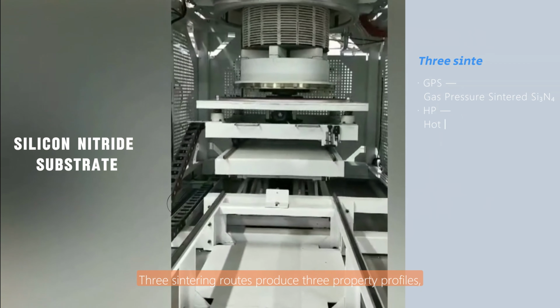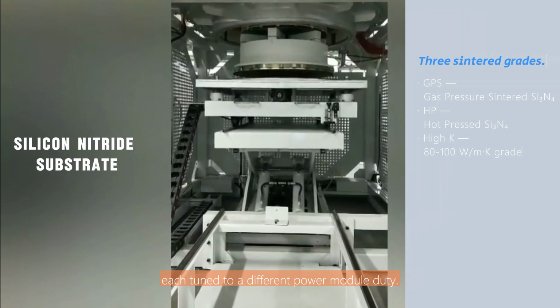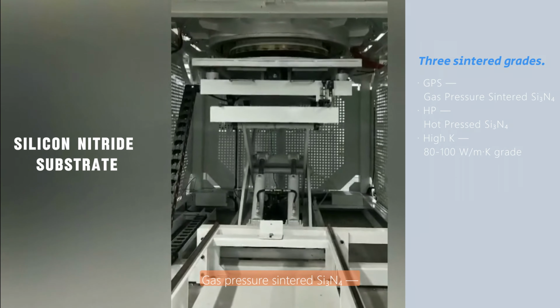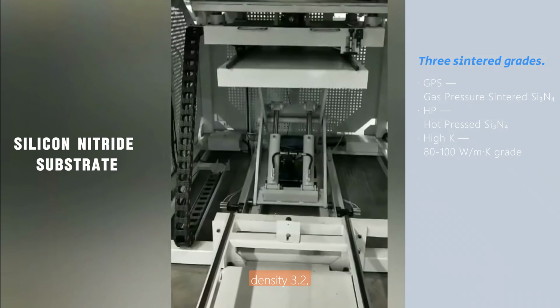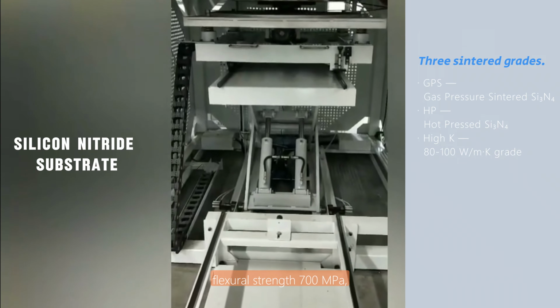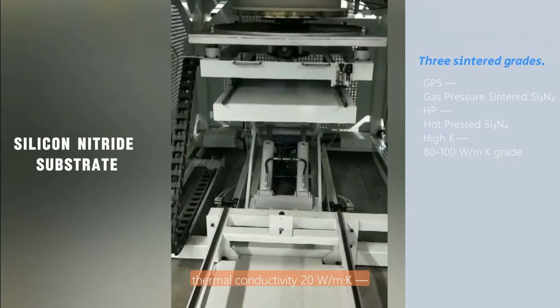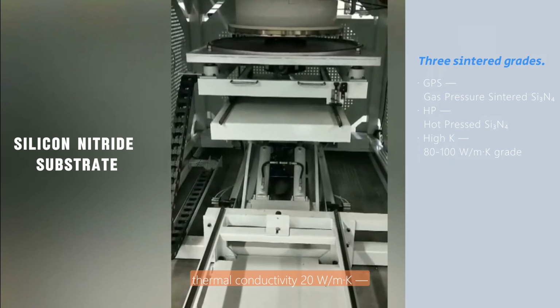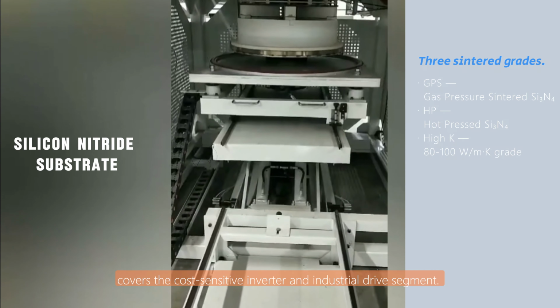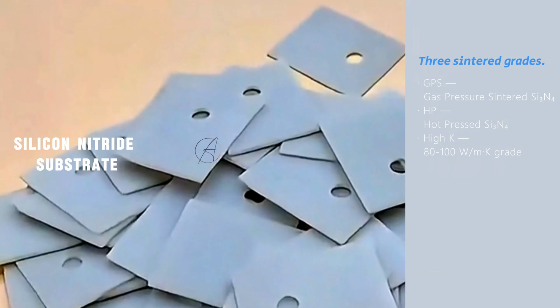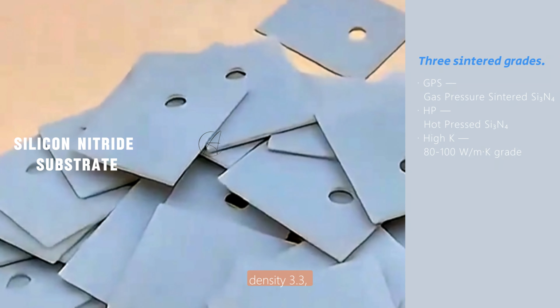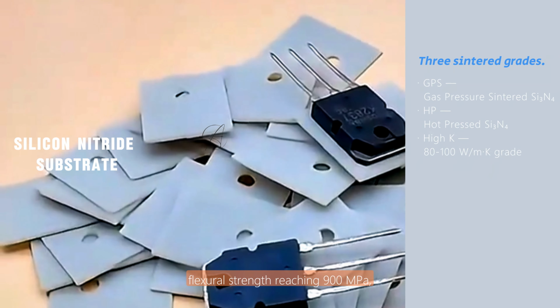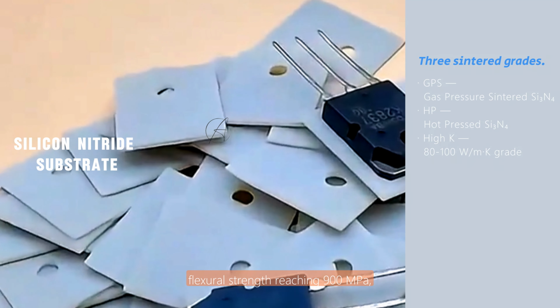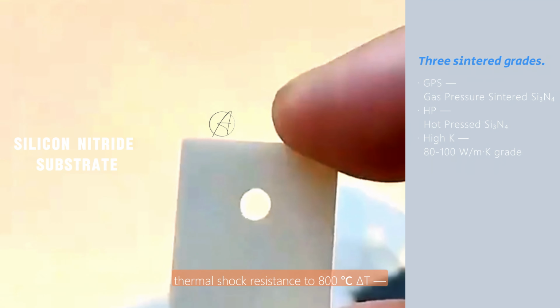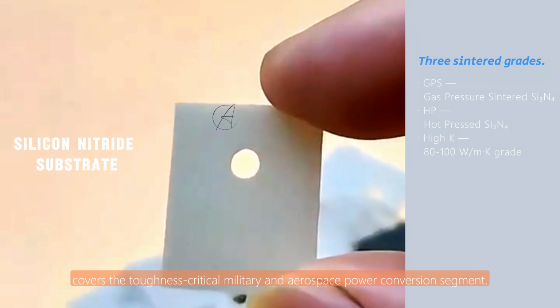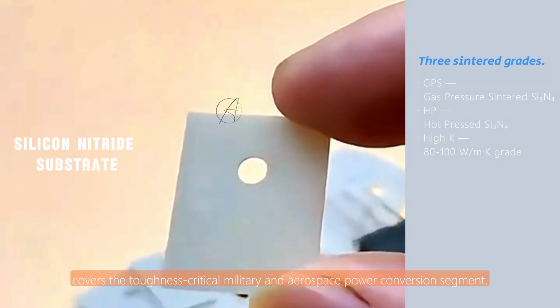3 sintering routes produce 3 property profiles, each tuned to a different power module duty. Gas pressure sintered silicon nitride, density 3.2, flexural strength 700 megapascals, thermal conductivity 20 watts per meter per Kelvin, covers the cost-sensitive inverter and industrial drive segment. Hot-pressed silicon nitride, density 3.3, flexural strength reaching 900 megapascals, thermal shock resistance to 800 degrees delta T, covers the toughness critical military and aerospace power conversion segment.